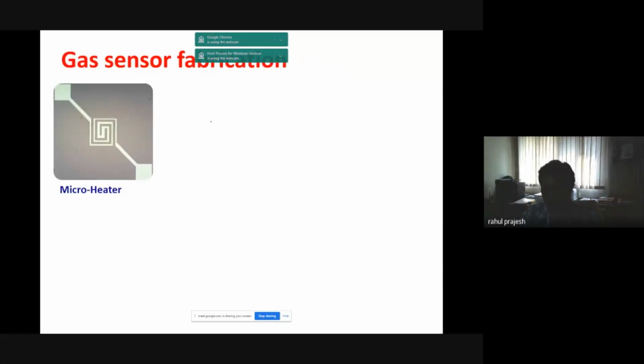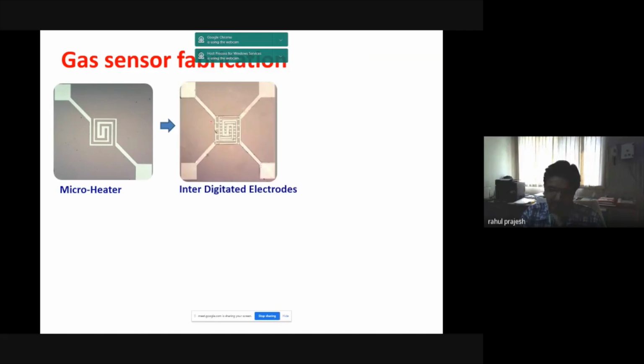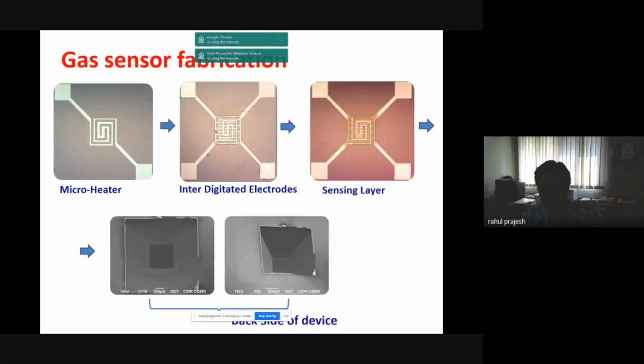Now, gas sensor fabrication. After you have the micro heater fabricated, electrodes are patterned on top of that, then the sensing film, and finally you remove the silicon from the back so that the thermal mass is very low and you can get the maximum temperature, so that the response is maximum.